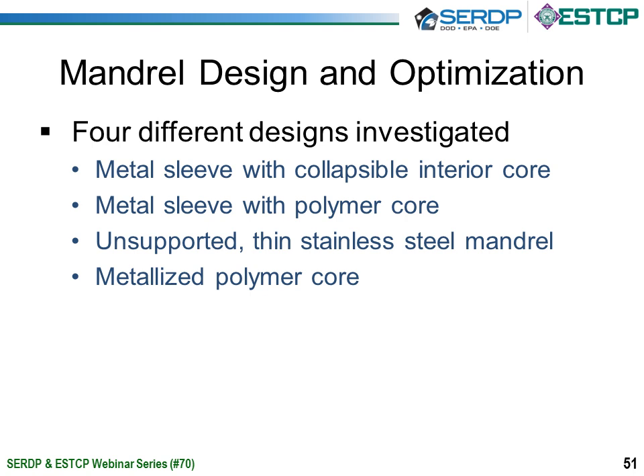In terms of mandrel design, we looked at 4 different designs. I probably could have used some images here, but we'll just go with my descriptions instead. The first of these was a metal sleeve with a collapsible interior core. The sleeve was prepared at Integran. It was a nickel cobalt sleeve. So you lock the core in place. It holds the sleeve rigid, you plate on top of that, and at the end of the plating process, the core collapses and is removed along with the sleeve.